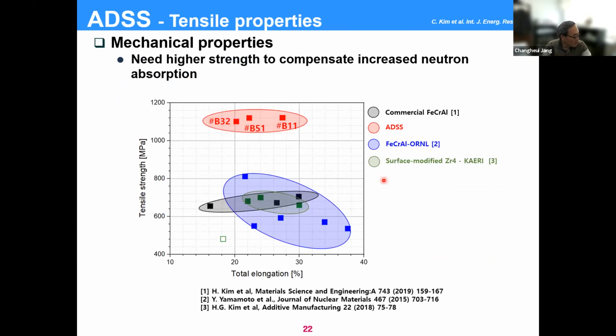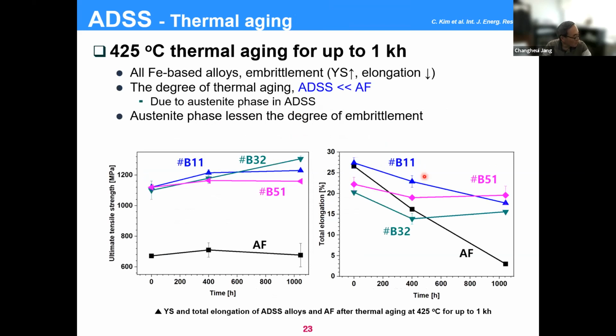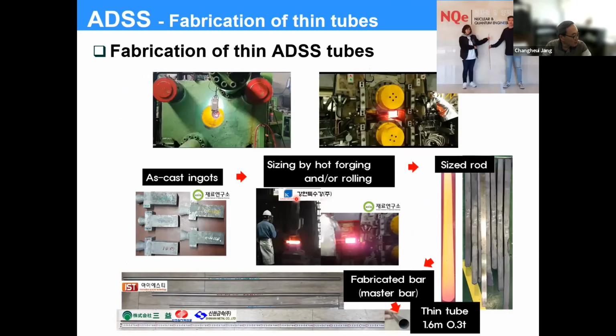And also we need a high strength material to compensate for some of the neutronics issues. So it should have high strength and a reasonable amount of ductility. Our alloys have higher strength and comparable ductility compared to other developed alloys. And because we have ferrite, we are worried about the thermal aging embrittlement issues. But as I said before, because our ADSS alloy has a certain fraction of austenite phases, the embrittlement caused by the ferrite was compensated significantly. So we can have roughly the same amount of ductility as the initial material, even though the strength increased because of the thermal aging embrittlement. And eventually, we produced a very thin-walled tube from the conventional pilgering process.